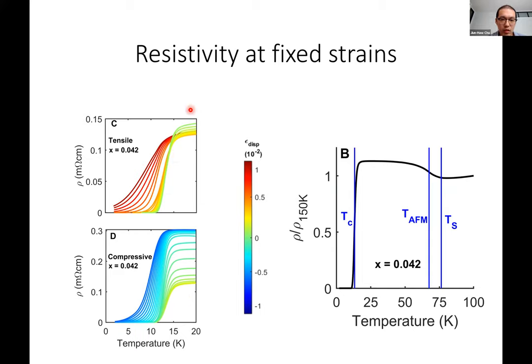However, if you look at the normal state resistivity, it changes a lot. The reason is that you're already in the nematic state, and you naturally form nematic structural domains. So the effect of strain in this range is really just aligning these structural and nematic domains. This large change of resistance is really just aligning domains either along the resistivity direction or perpendicular to it. So what you see is really the large resistivity anisotropy of the structural nematic domains.